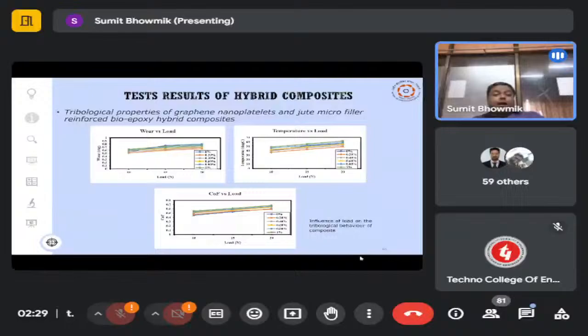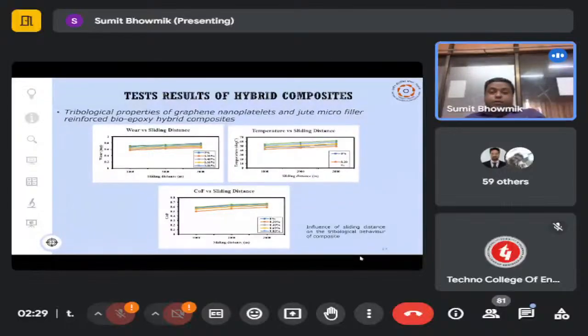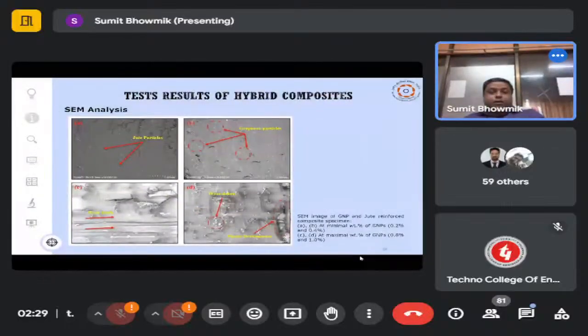Okay. Same way, tribological behavior was also investigated for both jute filler and graphene incorporated hybrid composite, and it has been found that with the increase of load, the wear is increasing, temperature is increasing, coefficient of friction is increasing for both, with distance and other behavior. This is because it follows a similar pattern to the property investigated without the hybrid composite, or normal composite material.